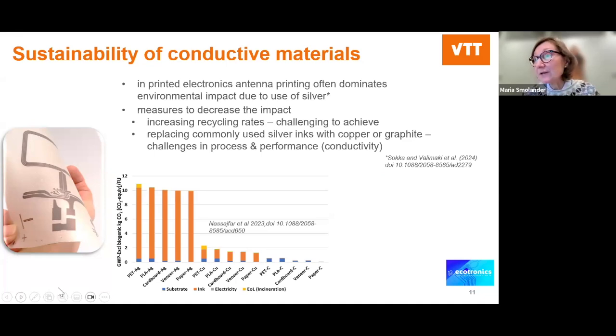the use of silver. So in this picture, for instance, it's shown that if we go from silver-based printing patterns to copper-based patterns, so this is printed copper, not etched copper, or to printed carbon inks, the CO2 equivalent is decreasing considerably, but this doesn't take into account the fact that the conductivity of copper and carbon is not on the same level with silver, and in some printed structures it's not even possible to use other materials. But sometimes, if the space is not limited and you don't need to go into extremely low line width, it might be beneficial to consider replacing at least part of the silver with another conductive material.